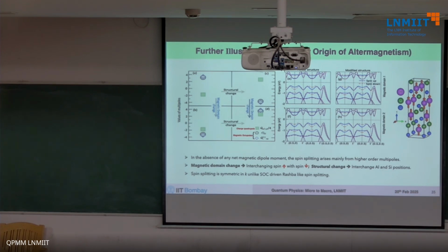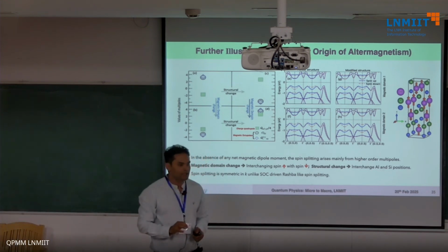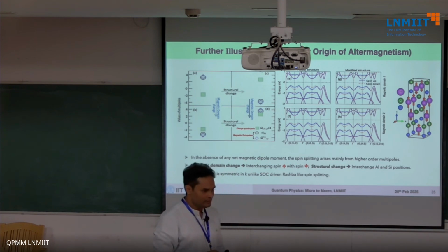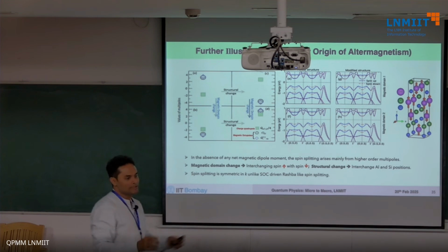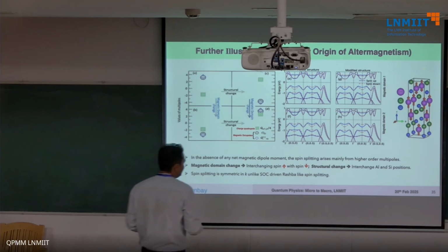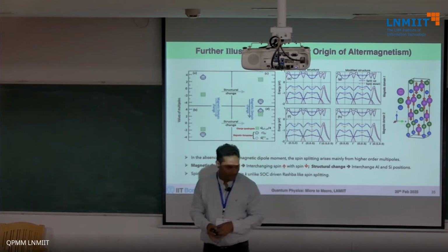It has to have a collinear antiferromagnetic ordering. Okay. You can't have DMI and stuff. Well, there will be DMI interaction, but it turns out that this splitting, which is non-relativistic in nature, is much stronger than your spin-orbit coupling. So they win over any consequence like anomalous Hall or anything like that. So one needs to find a system where this splitting is stronger.